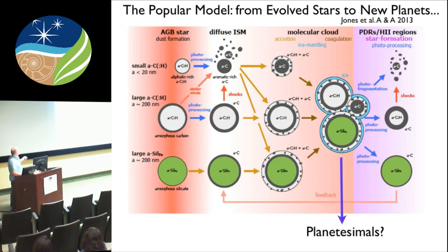The idea is that there's a connection between carbon formation, which involves stars, all the way to the formation of carbon in the reservoir, if you will, of carbon in the early star-forming region, say, in the early solar system. So the idea is an AGB star, a carbon-rich star, will form these various little particles. Here they're saying this is an aliphatic-rich particle with a slightly processed rim. Here's a larger one. The darker black is a more processed rim. And then here's a more silicate one with a little bit of organic solid on the outside.